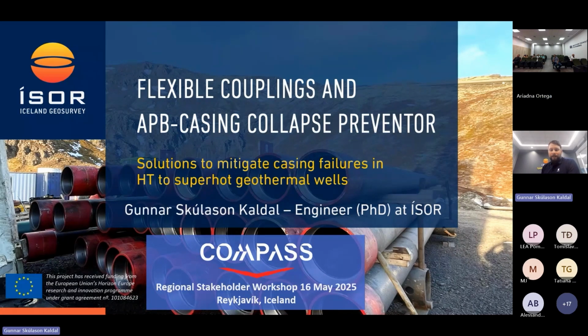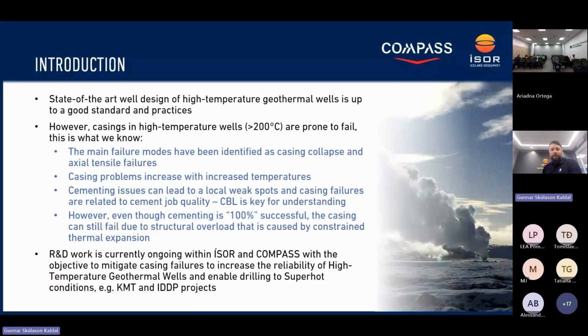So I'm Gunnar Skúlason Kaldal. I'm a mechanical engineer at ISOR, and I will talk a little bit about these challenges and potential solutions to the well integrity issues. So just to start, we already have good state-of-the-art well designs for high temperature geothermal wells. That is up to a good standard and practices. However, what we are tackling is that in high temperature, the casings are prone to fail. We can have failures in the casings, and the most common failures that we see are casing collapse and tensile failures of the casing. And we know that the casing problems increase with increased temperatures.